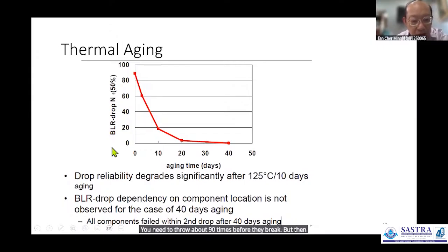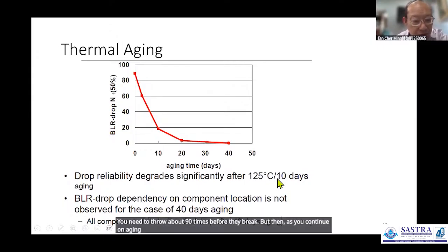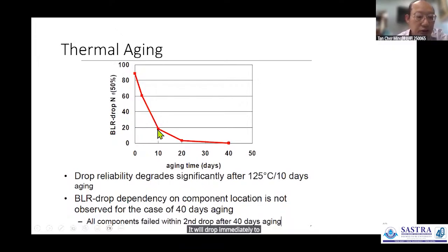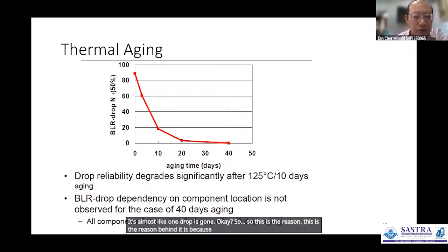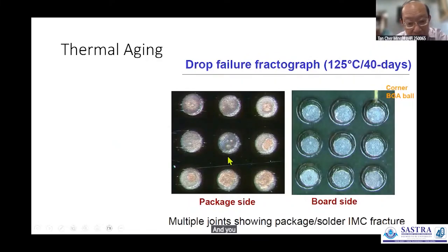But then as you continue aging for 10 days, it will drop immediately; you just need to drop 20 times and 50% of the solder will already give way. If you're aging to 40 days, it's almost like one drop and it's gone. So the reason behind it is the formation of the Cu3Sn. And you can see that it's totally broken.